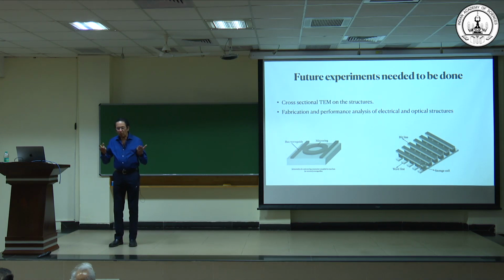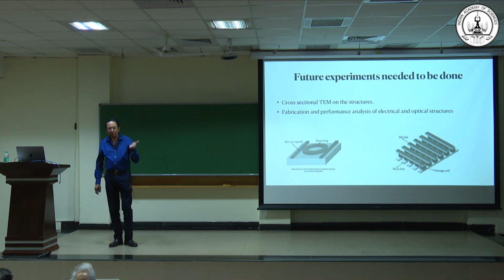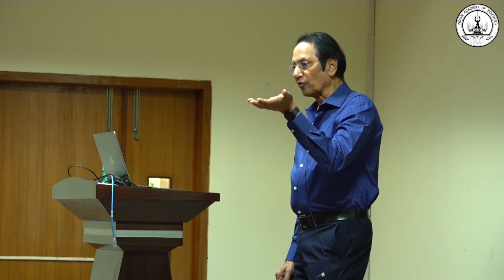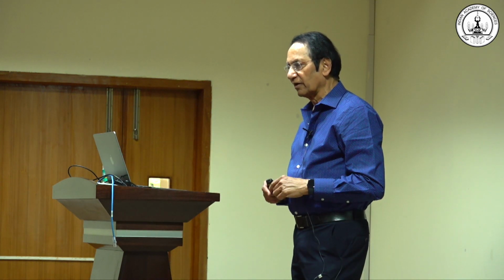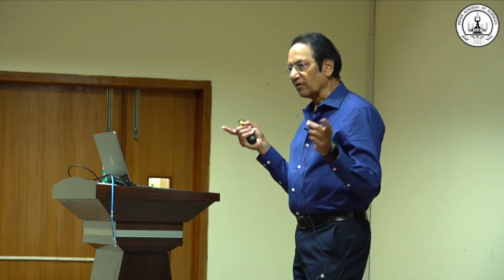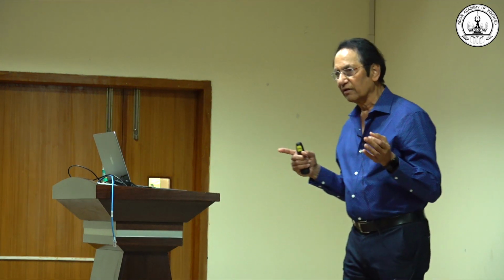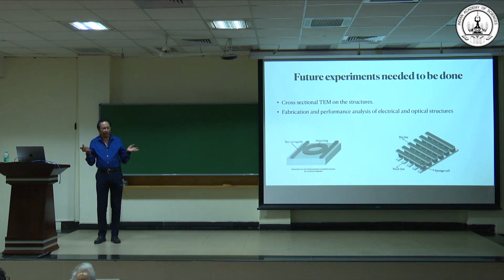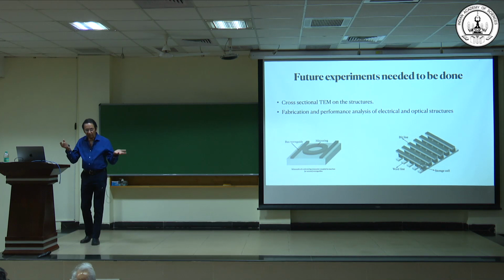The problem is that all the analysis techniques that we have today for looking at chips only work up to a few microns thickness. So when things get to 1 millimeter, 2 millimeters, nothing penetrates. Light doesn't penetrate because the ground plane will stop it. Heat will not go that far because the ground plane will diffuse the heat away, right? So the only things that penetrate are X-rays and magnetic fields. X-rays can only detect density differences, but the magnetic field can look at shorts and all that sort of stuff.